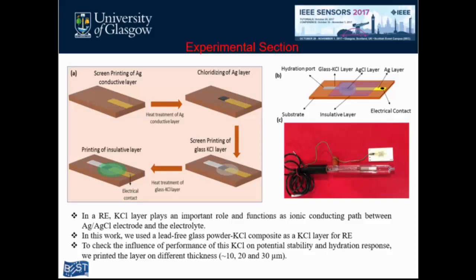As you can see here, I will first discuss how I fabricated the device. You can see an alumina substrate with a screen printed thick film silver electrode. A silver chloride reference electrode contains a silver layer coated with a silver chloride layer and dipped in a KCl solution. So initially I deposited a silver electrode by screen printing. After that, I converted the silver to silver chloride by chloridizing with a chloride solution.